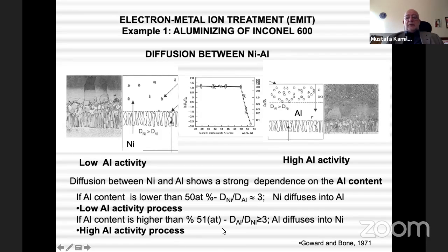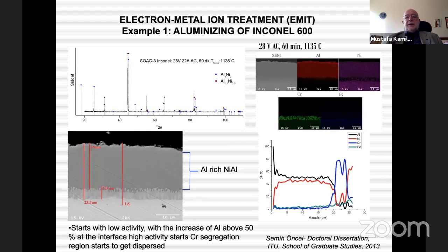On the other hand, when the atomic percent composition goes beyond 51%, if aluminum content becomes high, the process starts to become high activity. And in this case, aluminum diffuses into nickel. So when you look at these aluminizing processes, you see that both processes should take place concurrently, because at the beginning of aluminizing, we have a low aluminum content, then it switches to high aluminum content. So what we did, we applied a 28 volt AC voltage. By controlling this voltage, you can also tune the temperature of your substrate, and we end up with the formation of an aluminum-rich nickel aluminide layer.